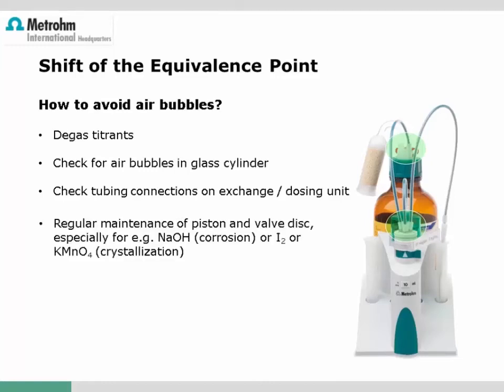But also the titrants might contribute to air bubbles. This might happen when corrosive reagents like concentrated alkaline solutions or reagents like iodine or permanganate, which tend to crystallization, are used. In both cases, the sealing lips of the piston might be scratched if crystals are formed, which results in a damage of the glass cylinder. Therefore, regular maintenance and replacement of such units is recommended, especially when such reagents are used.